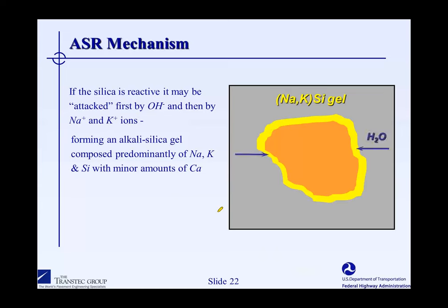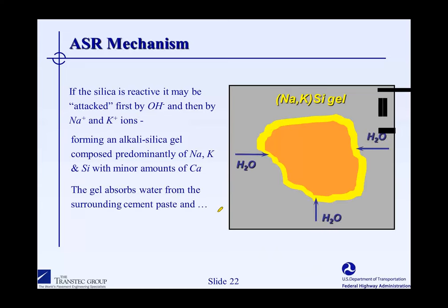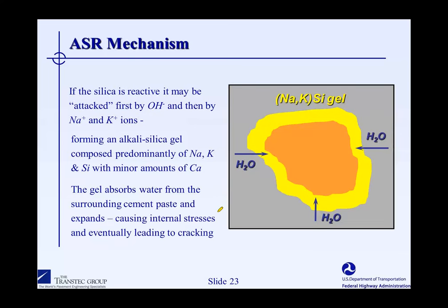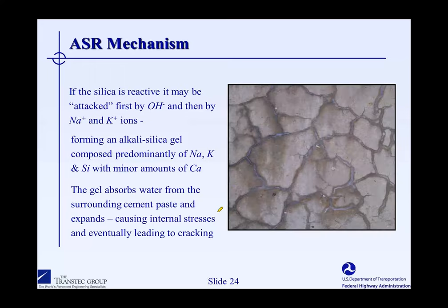That alkali silica gel is extremely hygroscopic, has a huge affinity for water, and will absorb as much water as it can from the surrounding cement paste. By absorbing that water, the gel basically expands. It starts to swell as it absorbs the water from the surrounding cement paste. And as the gel continues to expand, it will eventually lead to cracking of the surrounding cement paste. That is essentially our first sign of ASR when we're dealing with it in concrete: the swelling of the aggregate and the cracking of the surrounding cement paste. And we end up with an image that looks something like that in our concrete structure.